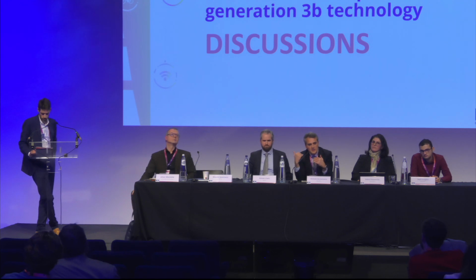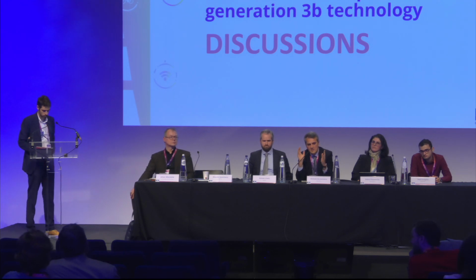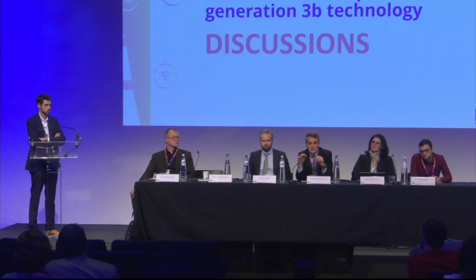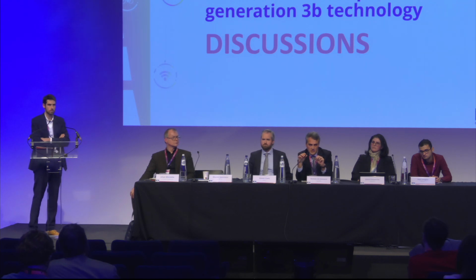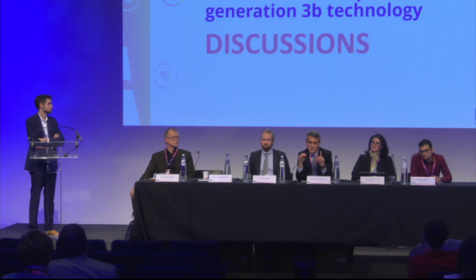as I showed in the results, this seems to be the way to go in case we want to produce a cell which has, I would not say a negligible, but a significantly lower capacity penalty when operated at high C rate. You start to see the benefits only when you go from 2C upwards. Up to 1C you don't see too much. So this is an extra step that you have to include in the cell production manufacturing. But that's pretty interesting, and that's transferable. That's a very important part.